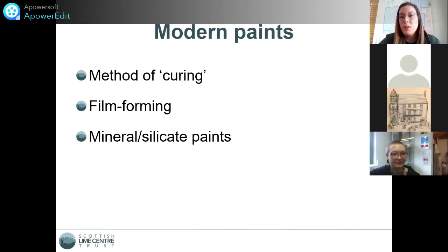However, lime wash, which is basically a suspension of lime, dries or cures much like a lime mortar. And so it's porous, it has a similar mineral makeup and pore function as the substrate it's being applied onto, so the lime and the stone that it's being applied onto. Modern mineral and silicate paints mimic that slightly, in that they also cure or dry similarly to lime washes, lime paints as well. It's just that they have various additives in them which make them a little bit more robust, more water repellent, and also aid pigmentation.